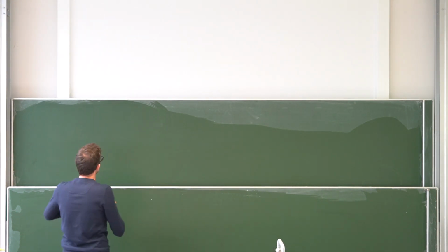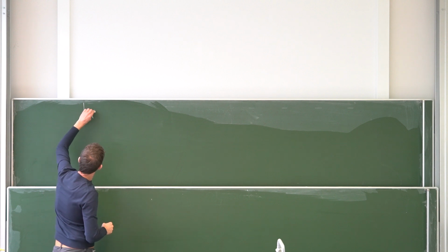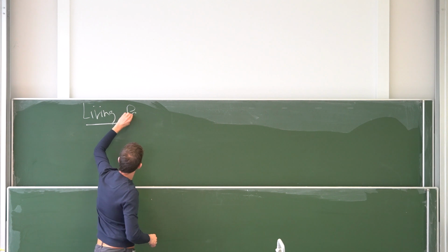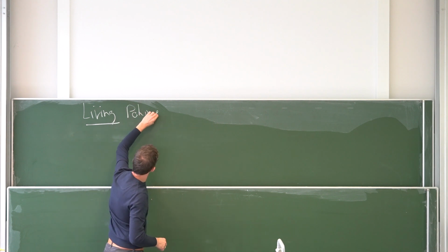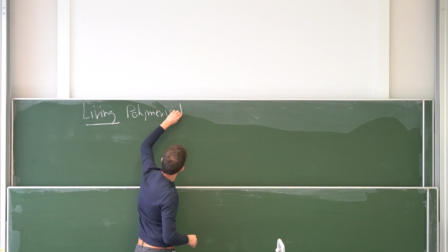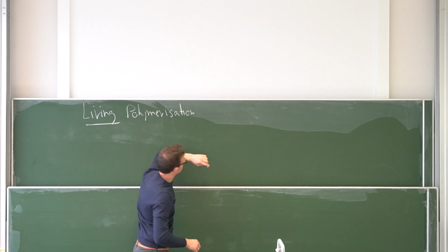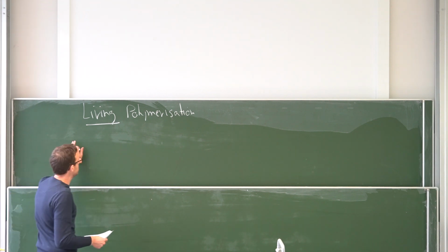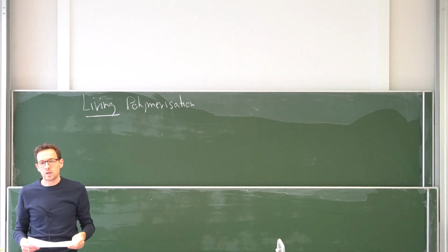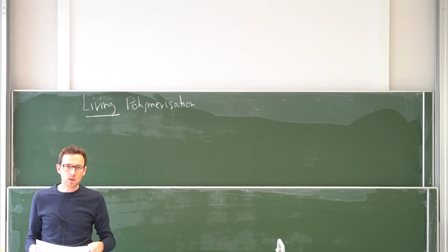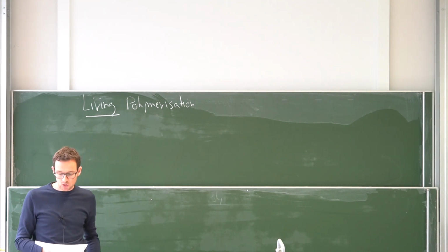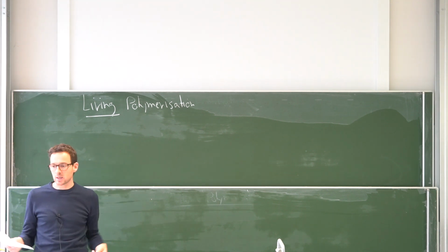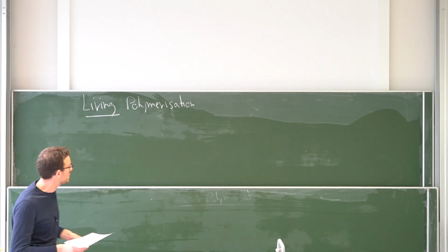So now, what does this mean? So first of all, anionic polymerization leads to this living characteristic, as we discussed, because there is no inherent termination reaction. And that means that the polymerization can go on and on and on as long as there are monomers present. So what does this mean?